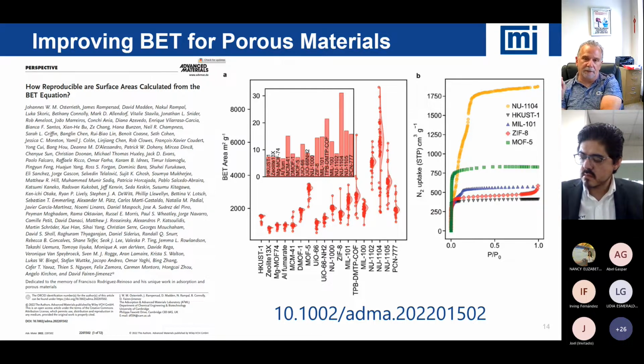Another piece that came out of some of these discussions, and it doesn't necessarily show up in this perspective piece, but it was discussed extensively at a Gordon conference in 2019, was we had multiple discussions on the fact that when you synthesize a material today, your material may be better than the original material that was synthesized. So for example, HKUST1, the current level of synthesis is far better than it was when the material was first reported. Because of that, surface areas for HKUST1, if you look at the different papers over time, the adsorption data is better. It has higher surface area, it has higher pore capacity.